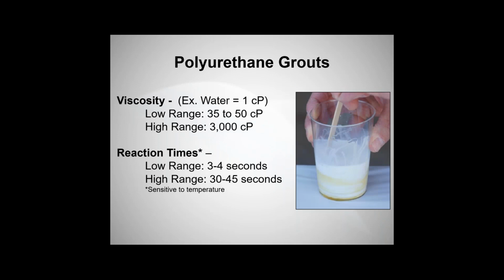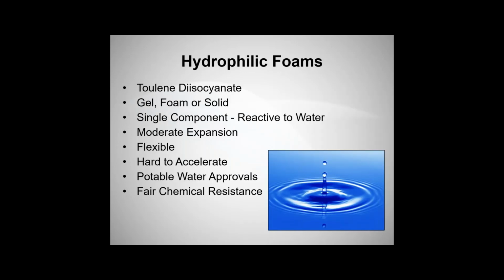Viscosities of the polyurethane grouts, regardless of whether it's a hydrophilic or hydrophobic, can range from 35 to 50 centipoise on the low end to as high as 3,000 centipoise on the high end. Reaction times can be a few seconds to as high as 30 to 45 seconds, or a minute or two, depending on what the temperature may be. They're definitely sensitive to temperature and the reaction times.